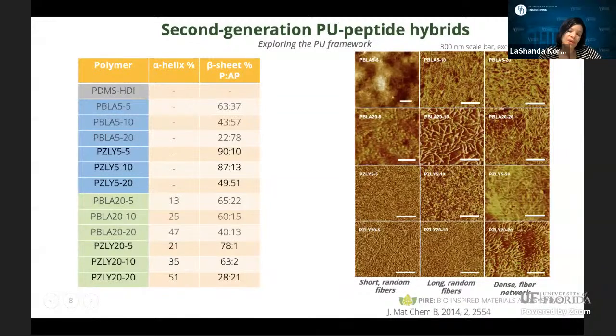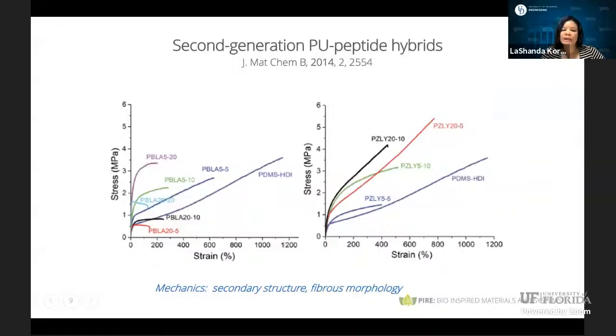But from the second generation, we really were able to confidently say that we can control secondary structure using this polyurethane framework, that we have molecular weight that's sufficient for forming nice films and then fibers I'll show a little bit later, and that we can now control the packing behavior and overall microphase segregated structure. Now, the emphasis here is not on being able to actually derive a specific type of mechanical property, but just to show the diversity with all of these different handles we have with this dynamic framework. So here you can see for both the PBLA series as well as the polylysine series, that you're able to both modulate the extensibility as well as the overall modulus of these systems through the control of both peptide block length as well as the composition of these systems.